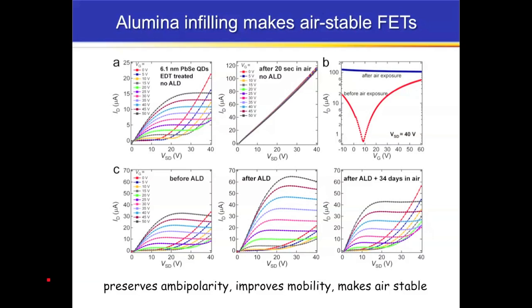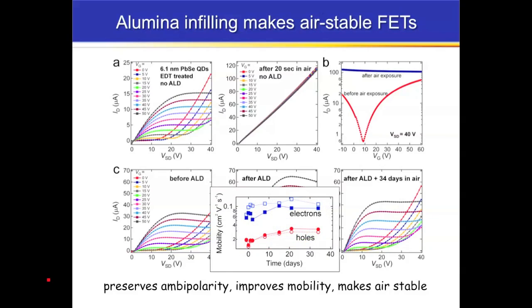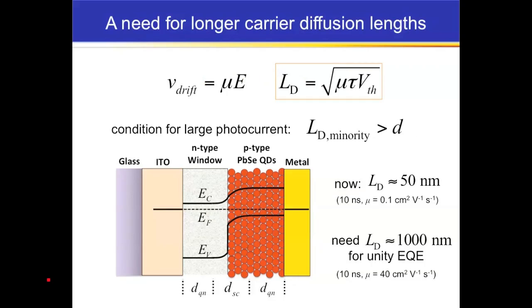But if we use our ALD technique, in this case with EDT-treated films, this is before and after ALD here, and then this is after ALD and 34 days in air. You can see you get some changes in the current, but the essential behavior is retained. We preserve the ambipolarity. The mobility actually improves slightly with time, just a little bit, and it makes these devices air stable over the long term. Okay, so we can actually go and study mobility now kind of on our terms.